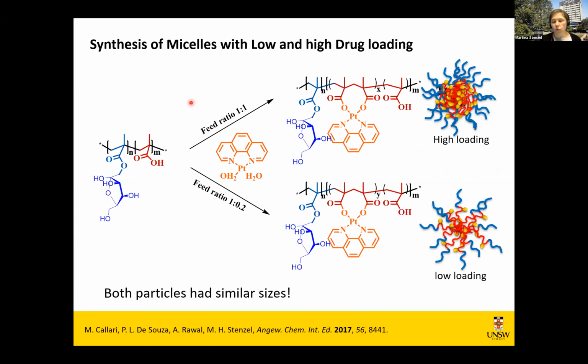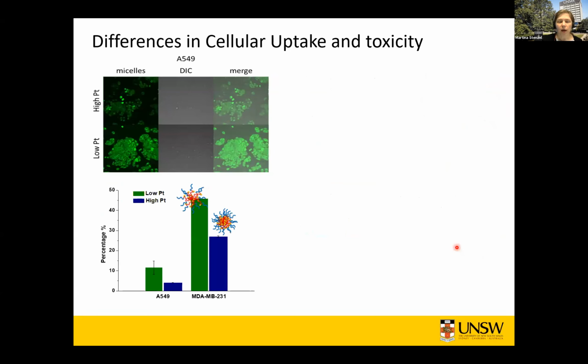So here we have 2 nanoparticles, and we load them with platinum drugs. Platinum drugs are very commonly applied anti-cancer drugs. And in one nanoparticle, we put in a lot of drugs, and in the other particle, we put in very little drug. So now we would like to understand what the cellular uptake is. And here comes the first surprise, because if we have only a little bit of drug in there, then we find that we get a much better cellular uptake than when we have a lot of drug in there.